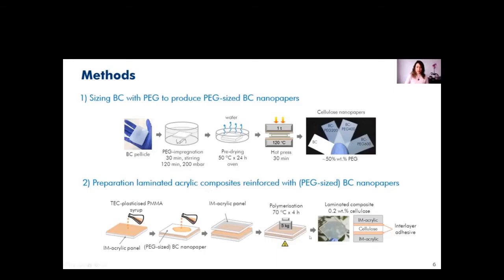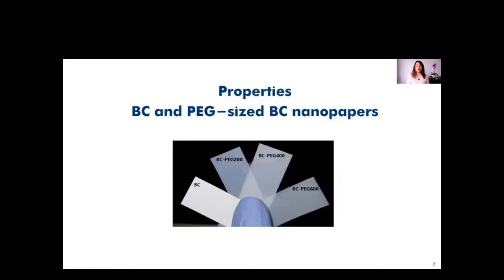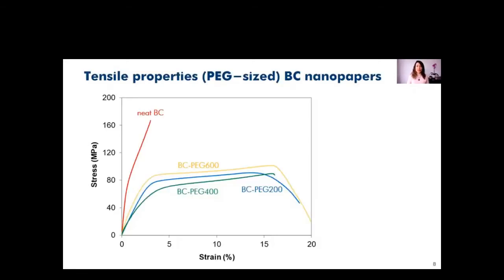And then we have the visual appearance of the composites. Now we will move further to the BC and PEG-sized BC nanopapers properties. The first one is the tensile properties of these nanopapers. We have the stress-strain curve, and then we have a neat BC in the red curve with approximately 170 megapascal of strength and 16 gigapascal of modulus.